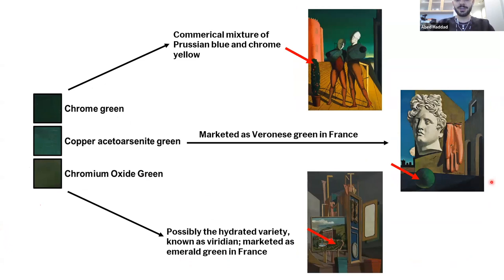For the greens, de Chirico lists three green pigments in his treatise: emerald green, Veronese green, and green earth. And in the paintings analyzed here, only chromium-based greens and copper acetoarsenite were identified. A chromium-based green was used selectively to create dark greens of the foliage in the Great Metaphysical Interior painting right here. But on the other hand, a green shrub in the Duo contains a mixture of Prussian blue and chrome yellow, which was sold commercially as chrome green, which can be kind of confusing between the chrome green and the chromium oxide green.